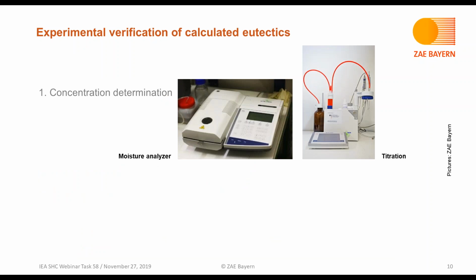Having predicted these eutectic compositions, it's important to experimentally verify the calculations. At first, it's important to determine the concentration of the salt solutions we are measuring. Therefore, we determine the water content using either a moisture analyzer or titration. A different type of titration is also used to measure the concentration of different salt ions. Then, having verified the concentration of the salt solution, we are performing calorimetry.